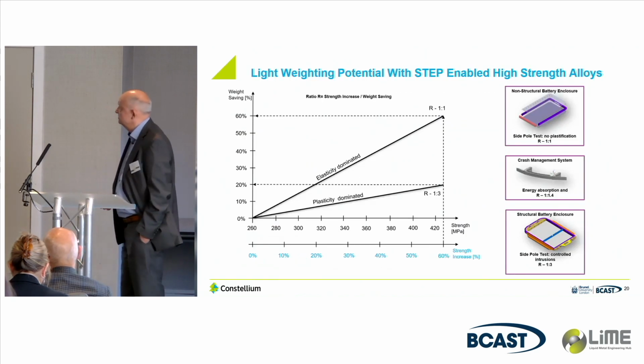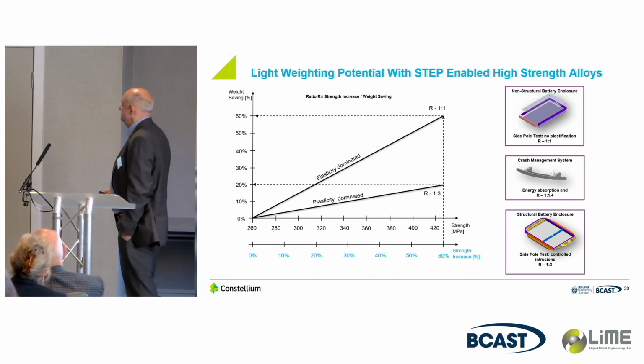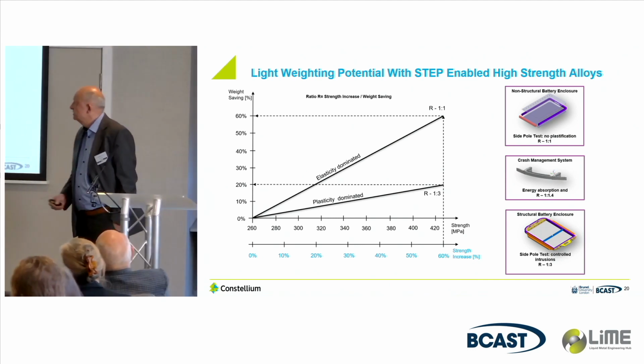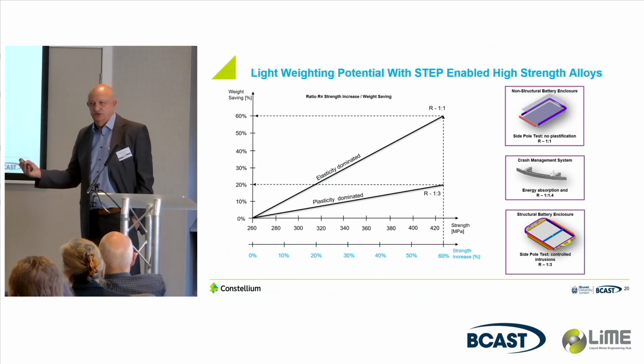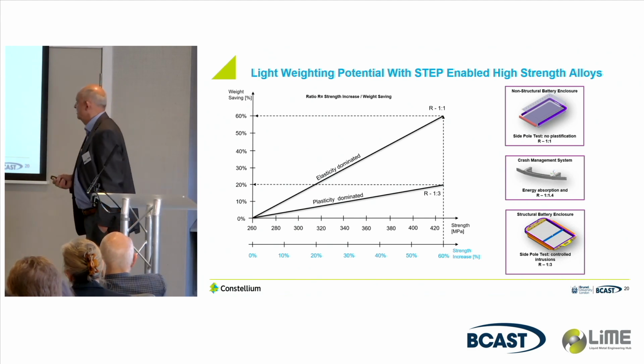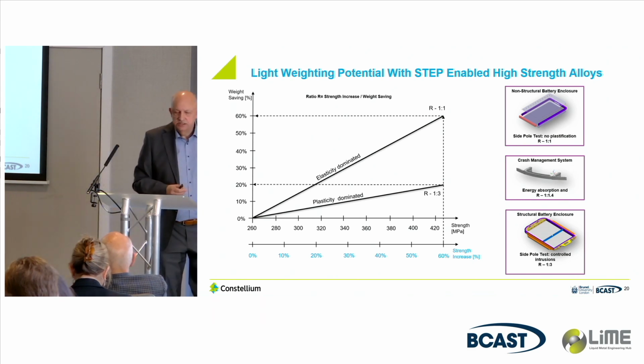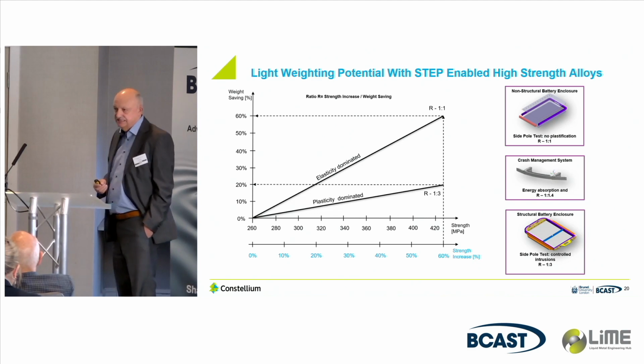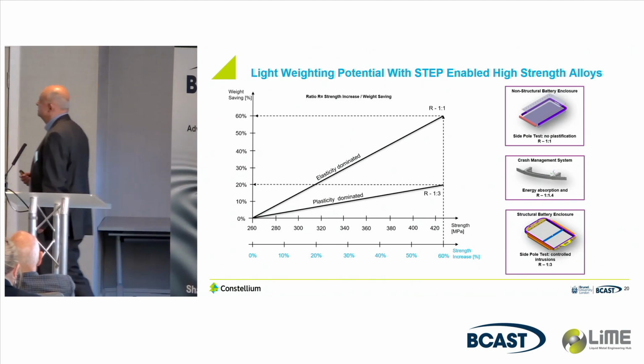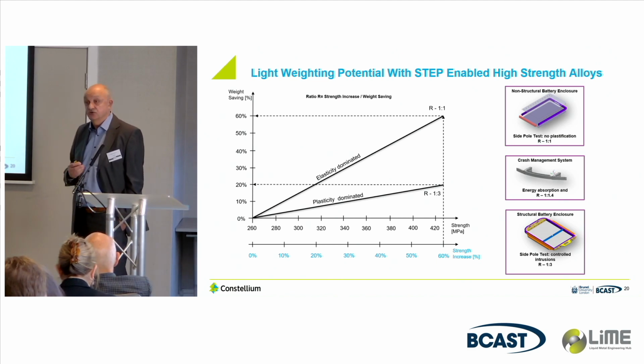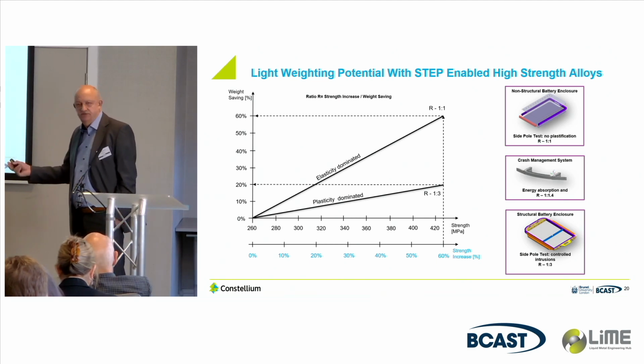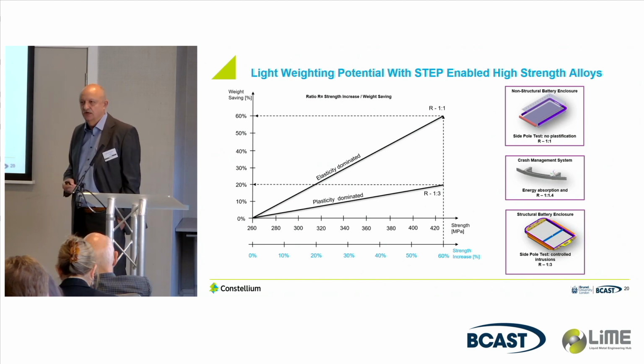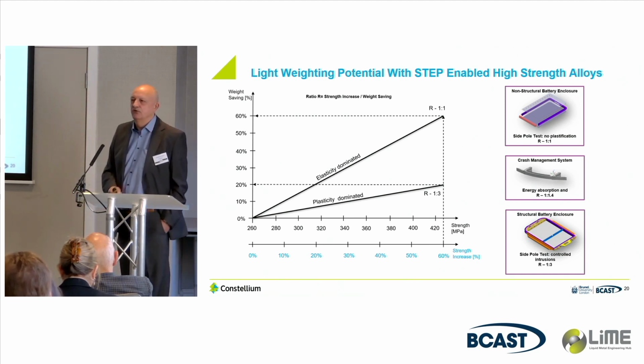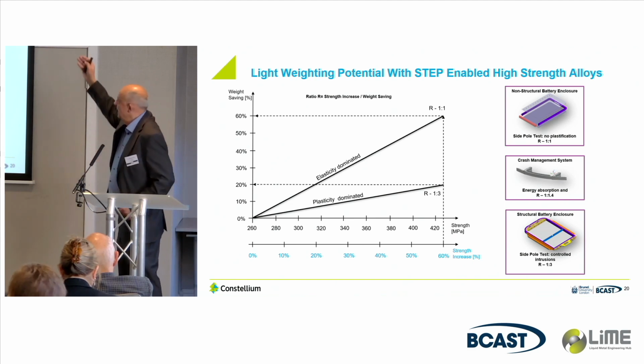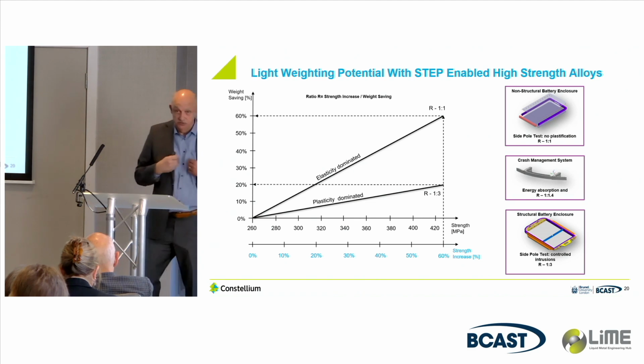And what that means in terms of our ability to save weight, if it's highly elastic dominated, then effectively we're saving the majority of weight. That's really where the maximum weight saving will come in. When we're into a high crash situation where it's plastically dominated, even though we can get quite significant improvements in strength, ultimately we cannot save that much weight because of the way the material performs in that structure. So that's part of the learning that's coming out of the program, and from our point of view, Constellium's point of view, how do we then take that and apply that to the different components that we manufacture?